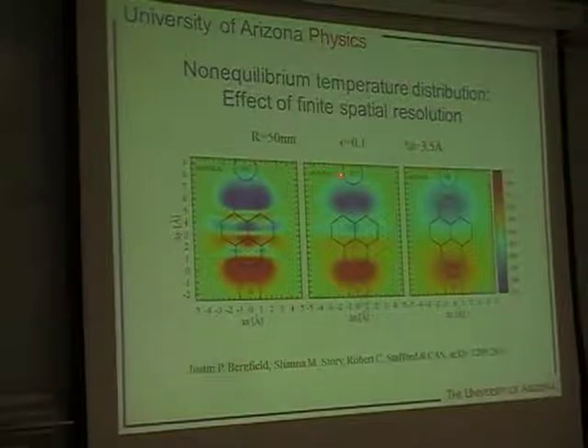And then what we've done here is, by hand, we've convolved the transmission function of the tip with a Gaussian with a half angstrom standard deviation. So you see it starts to wash out the interference pattern. Here we've convolved the transmission function of the tip with a Gaussian with a standard deviation of 1 angstrom, and now the interference pattern is completely gone, and all you can see is a thermal dipole.